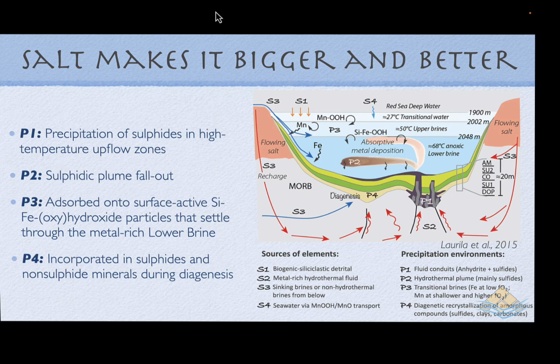And so the precipitation environments for those sources: P1 is the precipitation of sulphides in high temperature upflow zones, the typical VMS type deposits. P2 is the sulfidic plume fallout, and because there is an extensive area of brine stabilising that bottom layer, we see very extensive movement of P2. P3 is where we have absorption onto surface active silica iron hydroxide particles, and these have only become well documented in the last 2 decades, and then they settle down through that metalliferous lower brine layer and accumulate on the bottom. P4, the precipitation mechanisms are associated with ongoing aging and diagenesis within the sediment column.